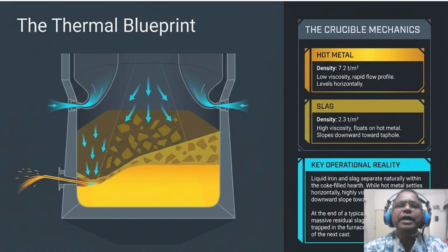Now look at the cross section on the left. We have a multi-phase system where liquid iron and slag separate naturally within a coke-filled hearth. Now notice the density delta. Hot metal is at 7.2 tons per cubic meter settled horizontally, while the highly viscous slag at 2.3 tons per cubic meter floats on the top, forming a sharp downward slope towards an active taphole.